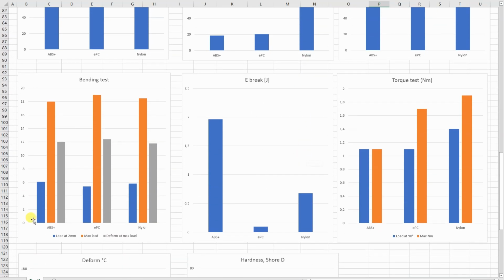And here you can see the bending test. Interesting, all three materials act very similarly in this test. And this was very impressive, the impact test, and this is just for reference actually, because the ABS Plus didn't even break. And even the nylon performed quite well in this experiment, and the polycarbonate was quite brittle actually. And this is the torque test. I don't know, maybe I wouldn't say that it's a significant difference.